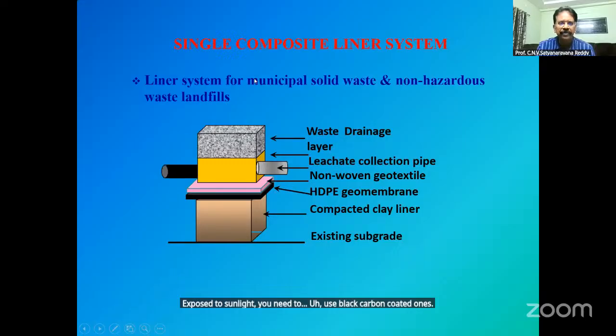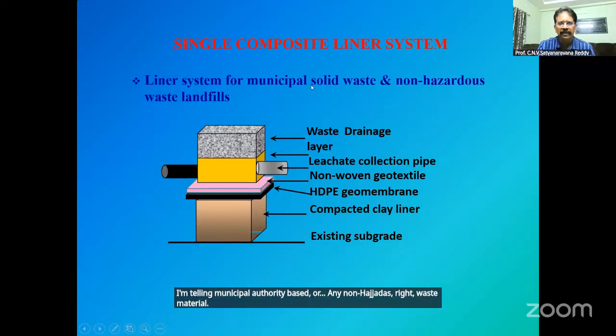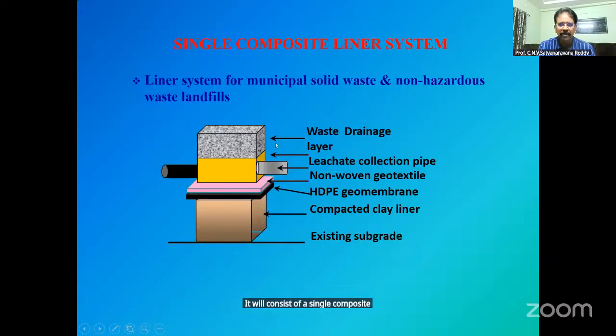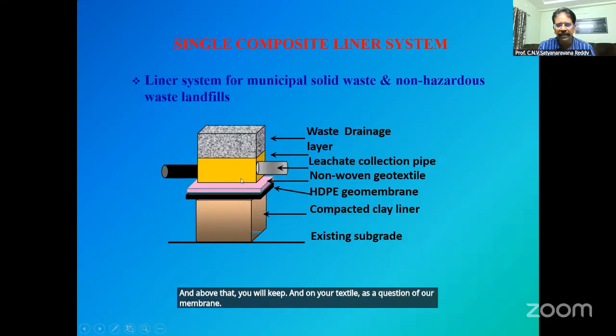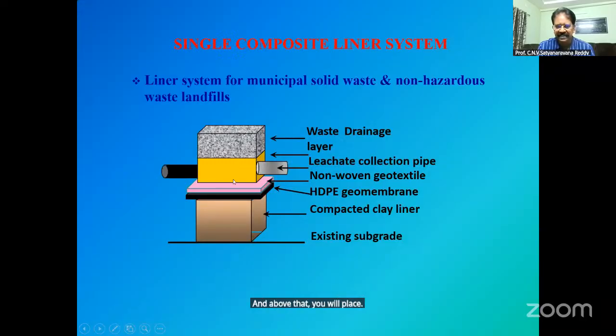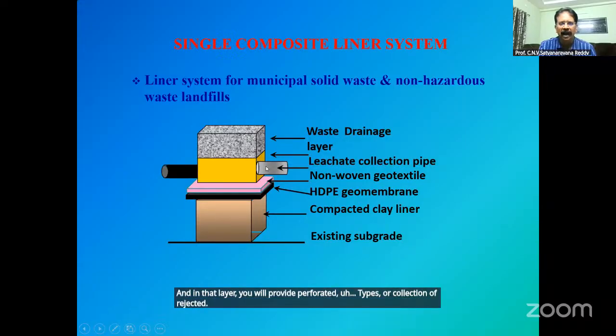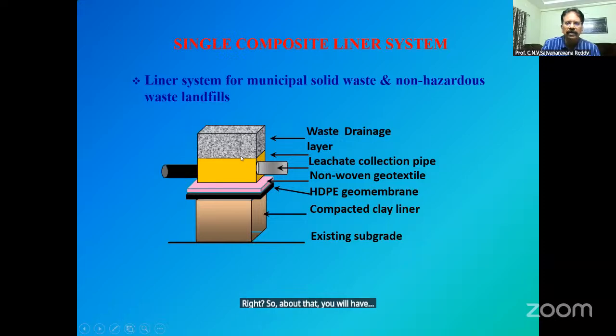So if you see the engineered landfill containing municipal solid waste or any non-hazardous waste material, it will consist of a single composite liner system. Before dumping waste, on the existing subgrade you will place compacted clay of 450 to 600 mm thickness, and above that you will keep HDPE geomembrane of minimum 2 mm thickness, and above that a non-woven geotextile as a cushion over the membrane, and above that you will place drainage material, graded sand, and in that layer you will provide perforated pipes for collection of leachate. Above that you will have waste material dumped.